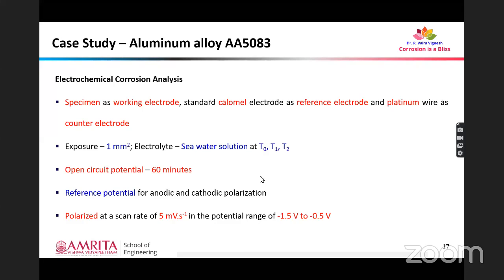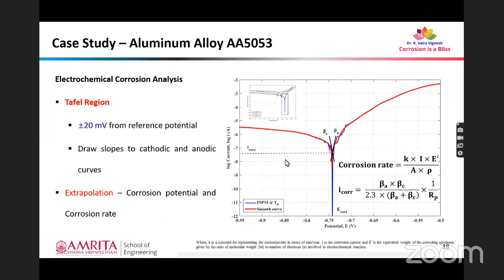The specimens will be subjected to polarization at a scan rate of 5 millivolt per second in the potential range of minus 1.5 volt to minus 0.5 volt. And this potential range differs from material to material. For example, if we take magnesium based alloys, obviously we have to go for more negative potential. Why? Because magnesium itself has more negative characteristics with respect to cathodic and anodic behavior. And this is how the potentiodynamic polarization graph looks. It will look like a V graph over here. The blue colored one is zoomed in for our convenience.